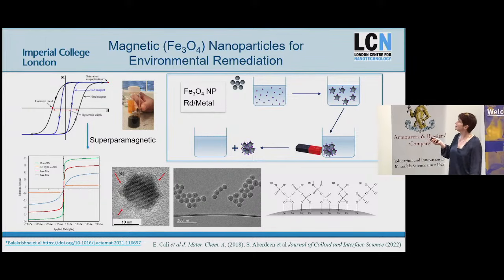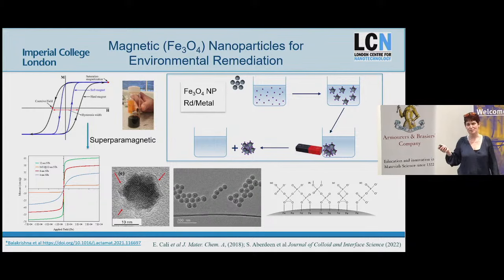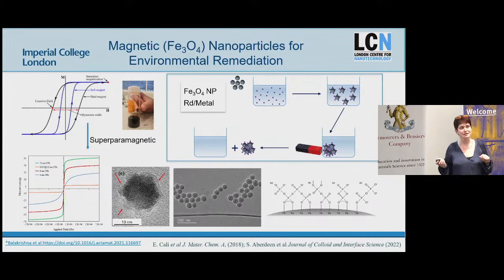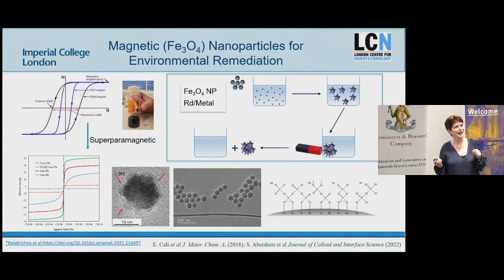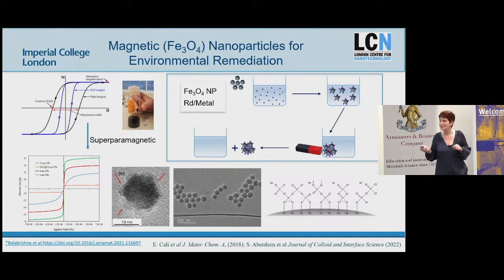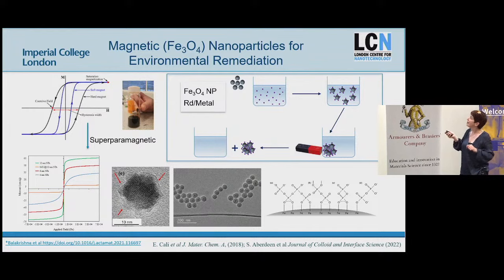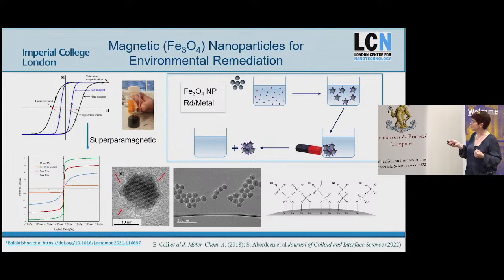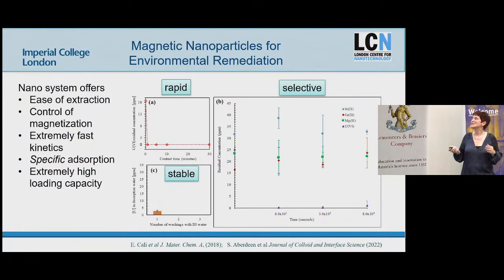So here's the idea. You take some nanoparticles, you coat the surface with something clever. This something clever in our case was based on phosphate, and because we know uranium ions, we hypothesize that uranium ions are going to really like phosphate. You mix them together, you use a magnet to pull them back out again, and you've got clean water and your nanoparticles with the uranium. So that's the idea. Obviously it works, I wouldn't be putting this in the slide, but anyway, no suspense.